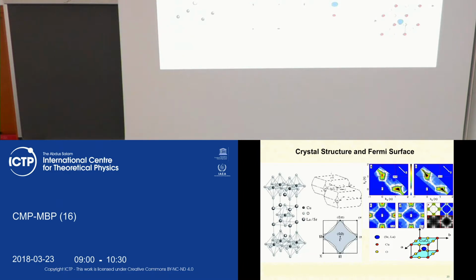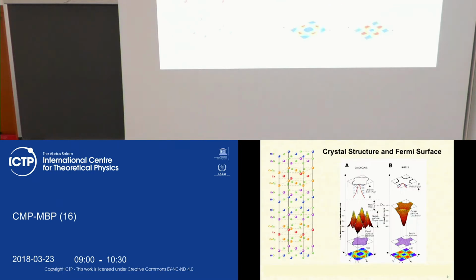In addition, you have a Van Hove singularity for the same tight binding model in the corners, which gives you yet another logarithm. So some of the correlation functions are divergent as log squared, and some of them are divergent as log, which was already a hint that one needs to find the direction which will then be connected to this divergent correlation function and produce a pairing mechanism. So to say, what we can learn from this slide is the shape of the Fermi surface, the quasi two-dimensional structure of the lattice, and the necessity to find a mechanism which will then couple this together.